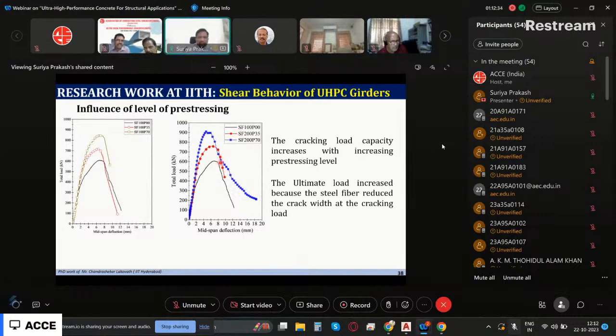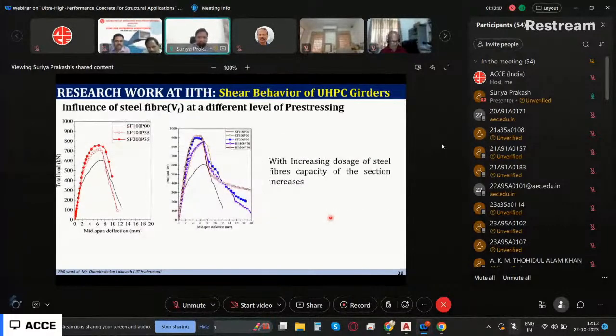And similarly, if I change the fiber dosage also, it is helping me. For example, if you look at P35 and P70, for the same fiber dosage, increasing the pre-stress helps in improving the performance. So that's what we said. And this is for 1% fiber dosage. P0 means no pre-stress. If you put 35% of your pre-stress, you get a performance improvement. 70% means further improvement. So the cracking load is found to increase with the amount of pre-stressing. Ultimate load also increased. So these are different things that we have understood from our research.